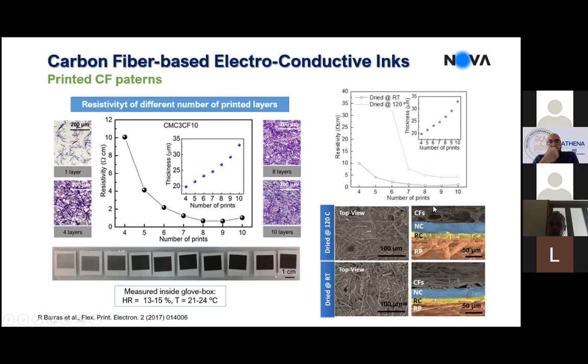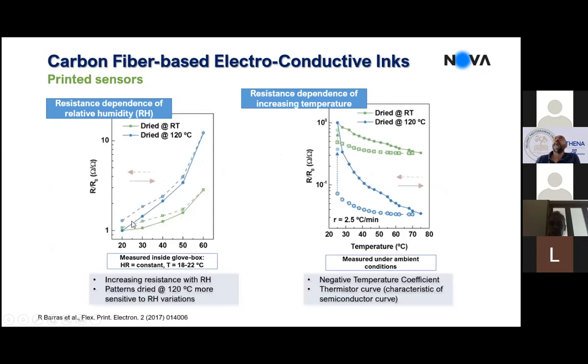So if you force drying, you end up with a pattern that is more, I would say, porous, or where the fibers are not so close to each other, the carbon fibers that provide the conductivity. So this seems to be bad in terms of conductivity, okay? But when you go for applications in sensing, this becomes good. Why? For instance, if you measure the humidity sensitivity of these printed layers, you have a variation in the resistance with the humidity. And remember that we have carbon fibers and CMC in the printed pattern. And indeed, the CMC, as I mentioned, is water soluble, so it means that it is a hygroscopic compound that will be sensitive to humidity. So it will absorb water, or the moisture, from the environment. And this will affect the way the fibers connect or touch each other. So let's simplify: you affect the percolation between the different carbon fibers that are in the film.